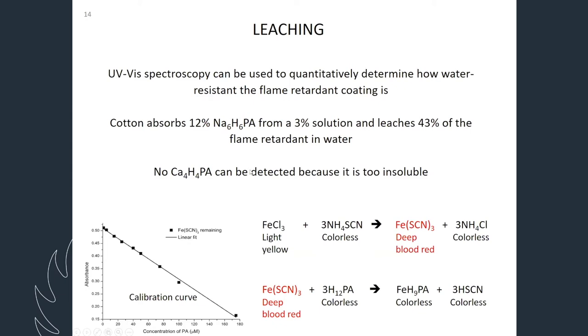We checked that when we have sodium salt of phytic acid, when you make a sample, it becomes 12% of the weight as phytic acid. But if we leach it, nearly half of it we lose because sodium salts are always more soluble. In a similar experiment, when we have the calcium salt of the phytic acid, we found there is no leaching. So that's quite stable on the cloth because we cannot detect any leached phytic acid in the solution.